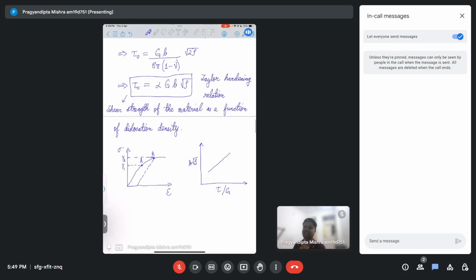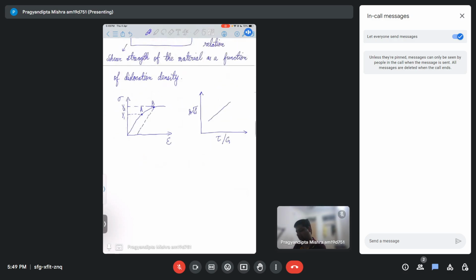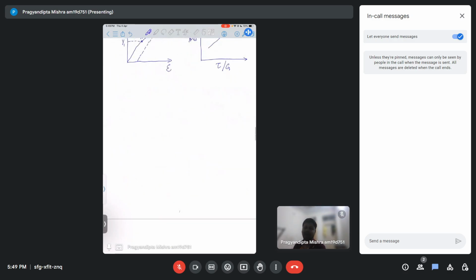So we can actually get a relation between the shear strength of the material as a function of the dislocation density. How much is the influence of dislocation density on shear strength? We can directly get a relation. So this is about Taylor hardening, or how the hardening works.